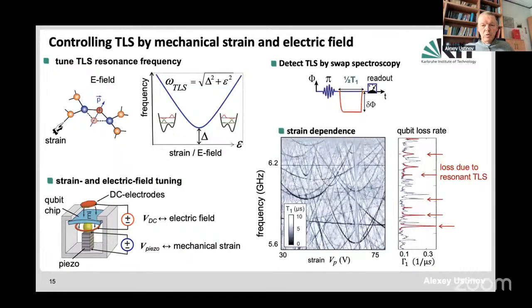So we observe the following. You see now the plot which you have seen horizontally on the previous slide. On the right, this very right plot is the frequency dependence of the qubit loss rate, and the resonances indicate coupling to the individual two-level systems. Now, on the plot to the left of it, you see in gray scale, again, the qubit loss rate. White spots are low loss and black spots are high loss, as a function of frequency, the vertical axis, and strain. And what you see very clearly is a lot of traces there. Those traces are individual two-level systems which vary their frequency in dependence on strain according to the textbook formula shown on the plot to the left above.